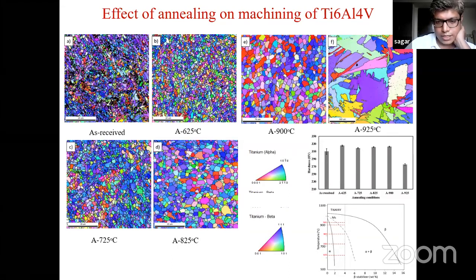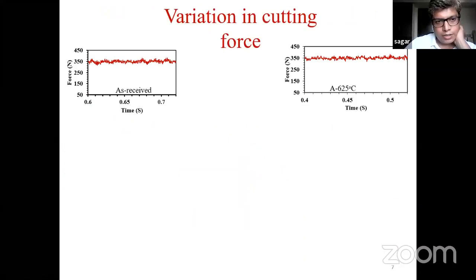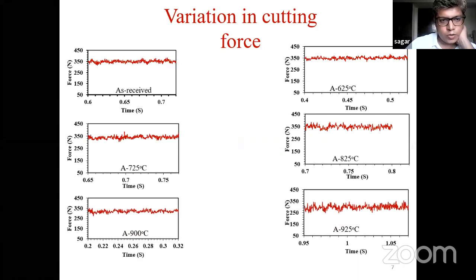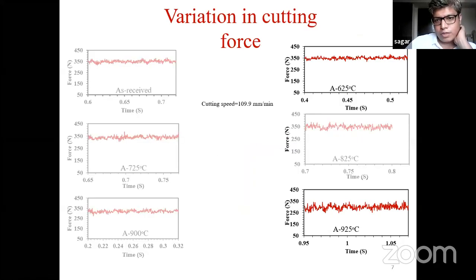So what we did next, we subjected all this material to machining. Here you could see I have plotted the cutting force with respect to time for every anneal condition. And if you observe closely the anneal 625 degrees Celsius and anneal 925 degrees Celsius, there is a huge variation in cutting forces for higher anneal samples. That means here we could see the grain size has affected machining.